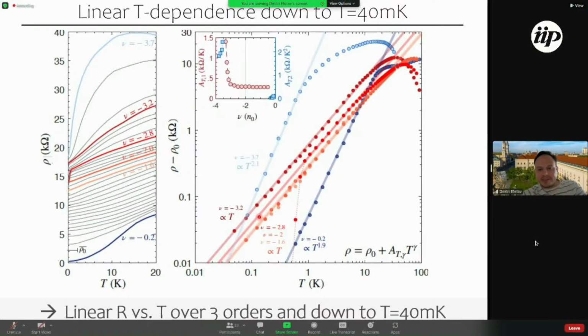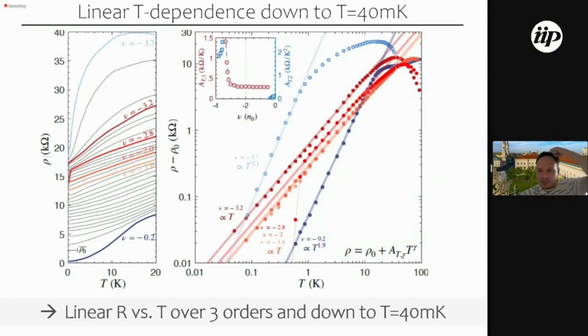And if we replot that data on a log-log scale, which allows us to see the low temperature regime a little better, we can trace these curves very precisely, and we can really convince ourselves that this linear temperature dependence persists all the way to 40 millikelvin, and from those 40 millikelvin, it goes all the way up to around 30 Kelvin.